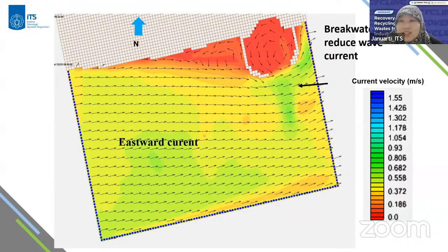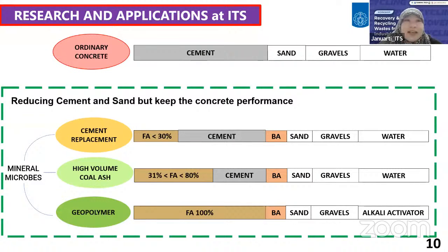And we've made a simulation here, the eastward current very near to Surabaya. And this is the north side. And in the simulation, we put a very small barrier here, a breakwater. And you can see this is the current velocity, the red means zero. There is no current velocity. So by constructing a very small breakwater here, we can see the current, from very high, can be reduced to zero. So this is the idea to put some breakwaters by using fly ash and bottom ash to protect Surabaya from abrasion.